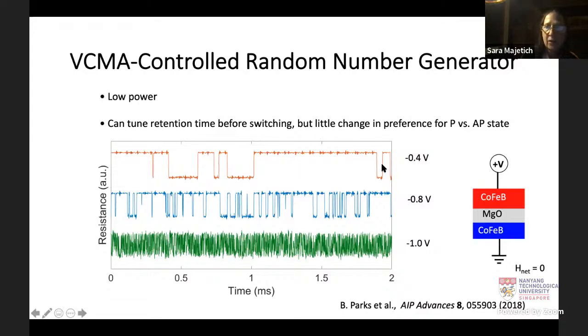And here's some data showing what happens as you change the voltage a few tenths of a volt between the average dwell times. I apologize for these little blips. That's noise from our other electronics. But we got long dwell times between switches. But what you see is that with a few tenths of a volt change, you can make the average dwell time shorter. And you can make it look like grass if you go to -1 volt. So you can have a big difference with a small difference in the applied voltage.